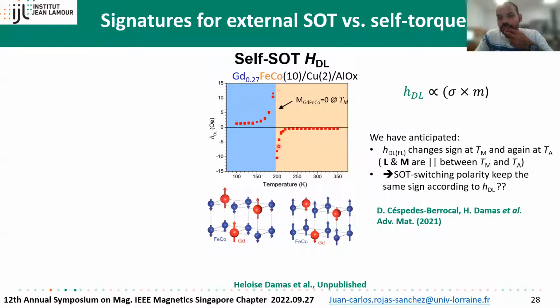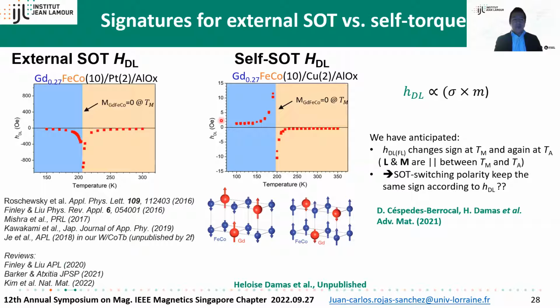Those are new data. How much? 2 minutes. Okay, thank you. That's fine. So here we observe that there is more data from my student Eloise. We can see here that in the self torque we have this change of damping-like, and here in the external spin-orbit torque the damping-like does not change sign on crossing the magnetic compensation temperature. So we don't observe the second change of sign that we predict here, because the signal here is very, very weak.